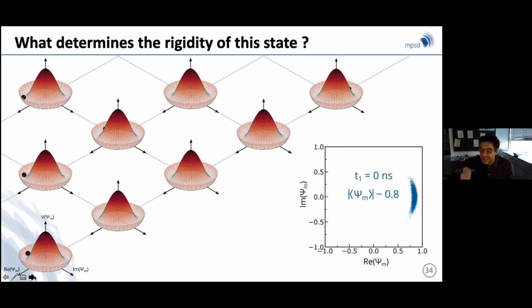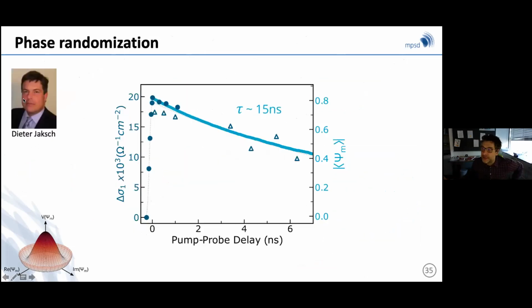and nucleates phase slips. And actually a calculation by our colleague Dieter Jaksch, who has been helping us try to understand just on the basis of a time-dependent Landau-Ginzburg formalism, we have been able to fit the relaxation time of this zero resistance state by simply considering what the phase diffusion would be in a highly superheated superconductor with the microscopic parameters of potassium C60.